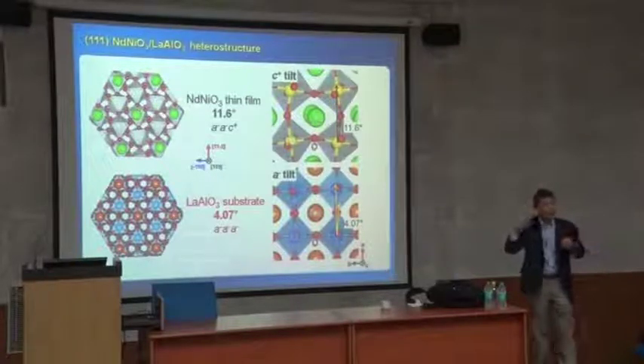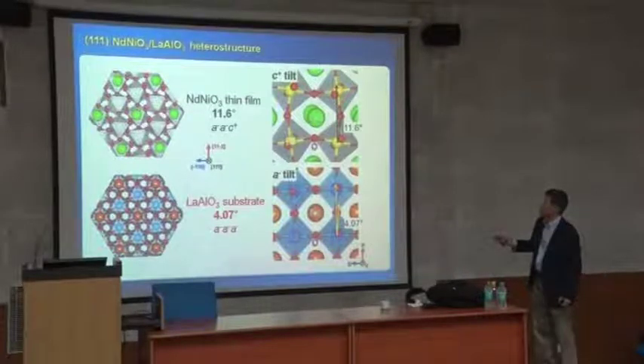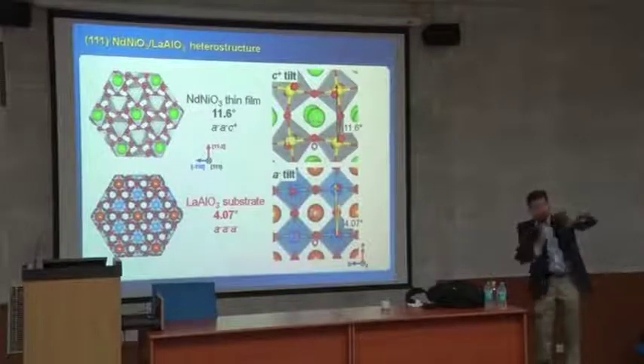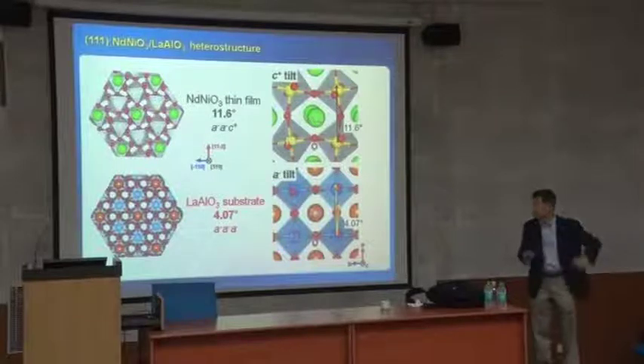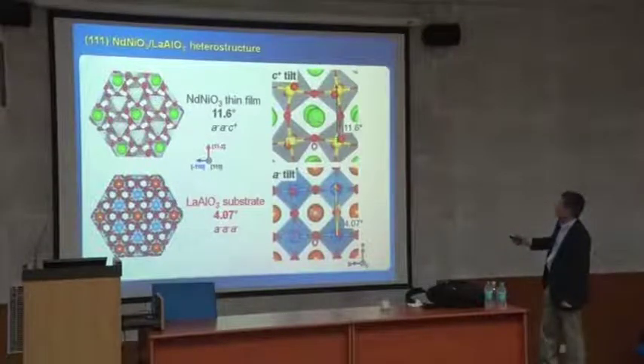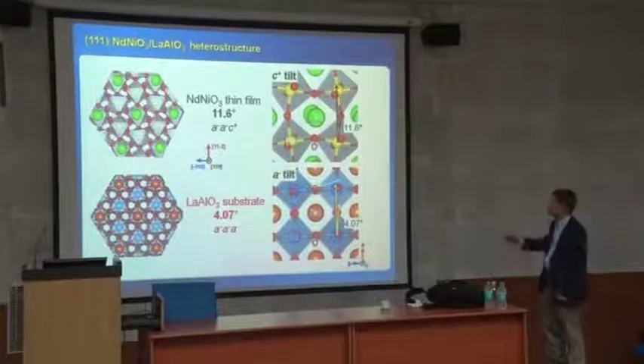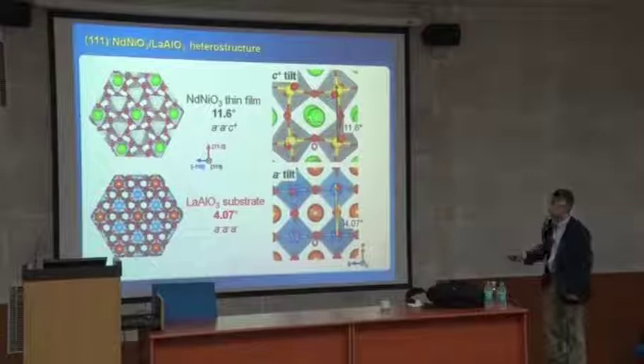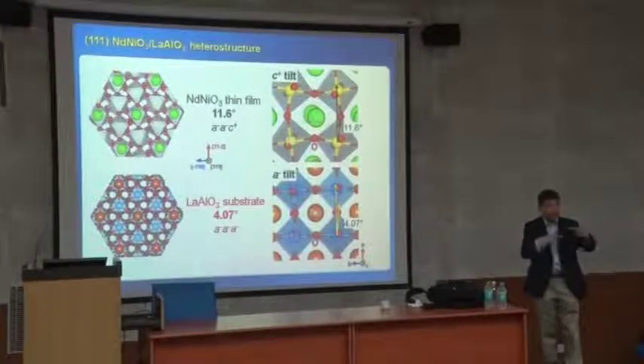You understand this basic concept? So that means this one, the tilting angle is very high, 11.6 degrees, the rotation is large. And then you have this one, a very small angle. So that means you have a large angle and a small angle, but the opposite one, then you actually try to rotate it, you stop somewhere. Okay? So stop somewhere. That's the pattern here. So this angle is big, and this angle is very small, and then you're trying to connect this one, and it's a very rigid substrate, and this one will shrink much smaller. But at the same time, when you stretch it, this A-site cation is going to go from antipolar to polar. The net is non-zero.